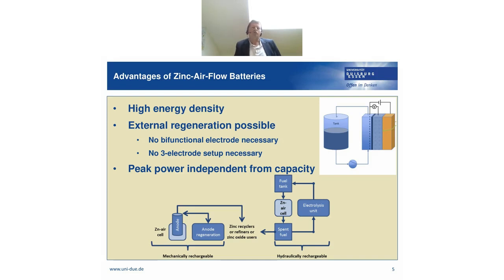So our approach is to use zinc slurries for the zinc air flow batteries. And the advantage is they possess a high energy density, as you can see here on the picture on the right top. The slurry is in a tank, and the slurry is pumped with the help of a pump through the anodic compartment. We have a separator, and on the cathode side, we have an oxygen electrode.